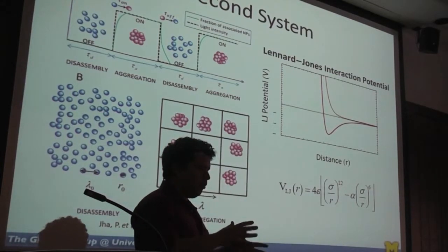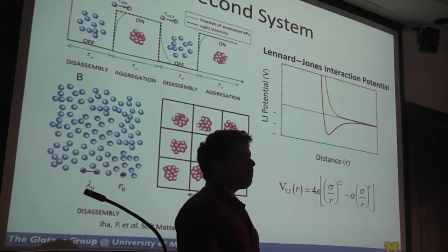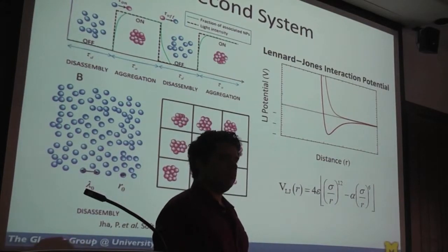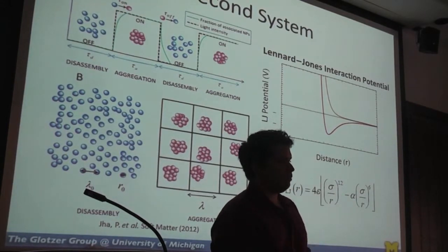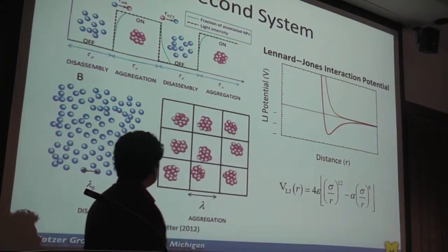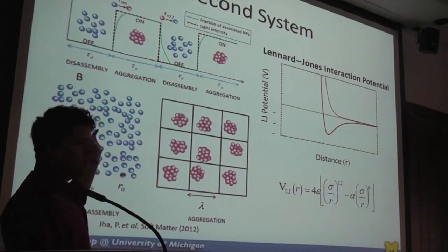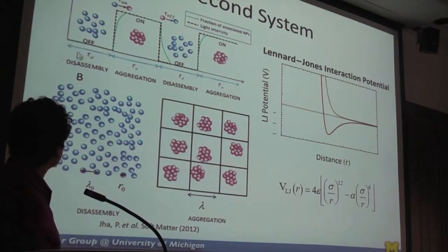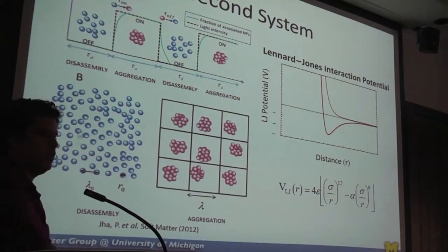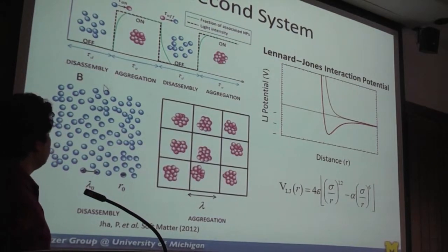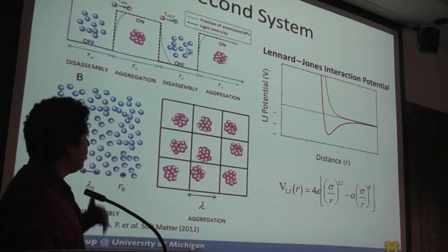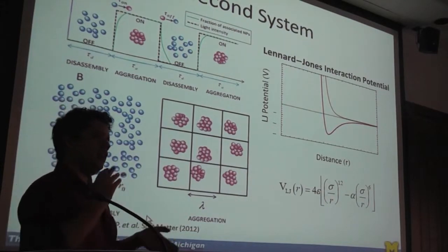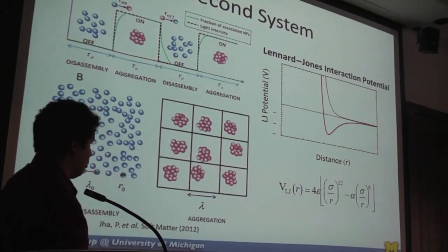So when there are nanoparticles with a surfactant attached to them, you can turn that surfactant by shining a light between hydrophilic and hydrophobic. Right? So when they're in one configuration, they don't want to come together, like in this case, in the off time, and then they just diffuse through the system. When you switch the light on, you can turn the interactions on, and then they come and aggregate together. And this is a reversible process. By switching the right wavelength of light, you can switch them on and off, repeatedly.